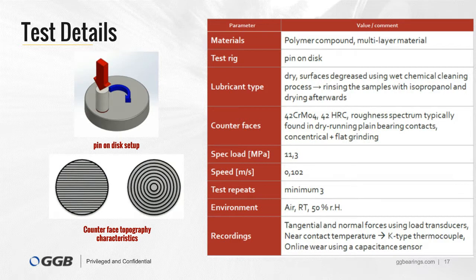The tribological tests were operated at one constant PV combination. The contact pressure was about 11.3 MPa in combination with a continuous sliding speed of 0.1 meters per second. The lubrication state was dry, and the samples were degreased using a wet chemical cleaning process before we ran the test.